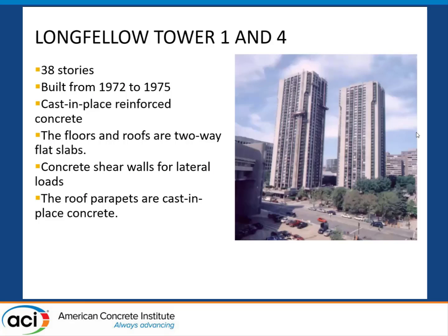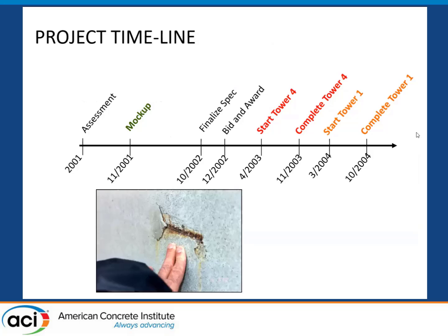These are twin 38-story condominiums, again located in downtown Boston. They were built in the 1970s, utilizing reinforced concrete. The project timeline for the job, and this was hence the reason for the adjustment in the title: the assessment was done in 2001. They did a mock-up toward the end of 2001. And what I liked about this approach was they actually built into the schedule to do a mock-up, and then they monitored it for a year before they finalized the specification and then went on to construction. We don't always have that luxury, but it's a great approach to first test out what you plan to do on two 38-story buildings before you complete the job.